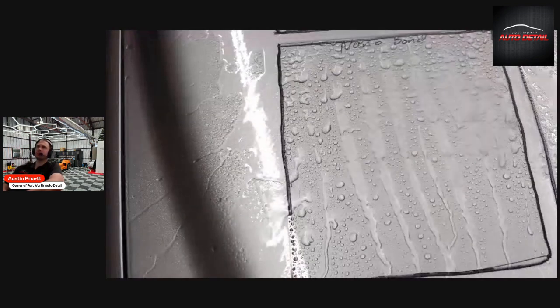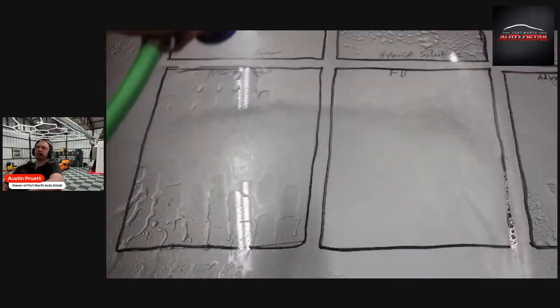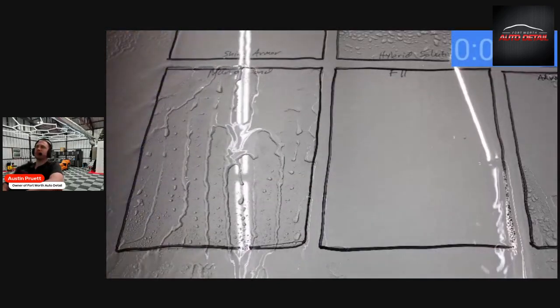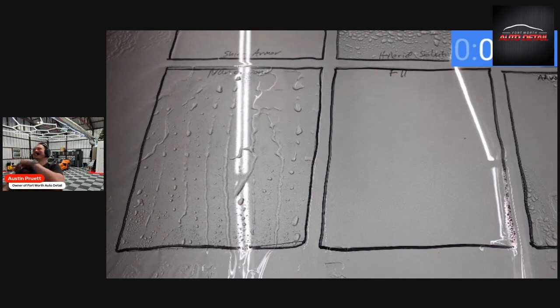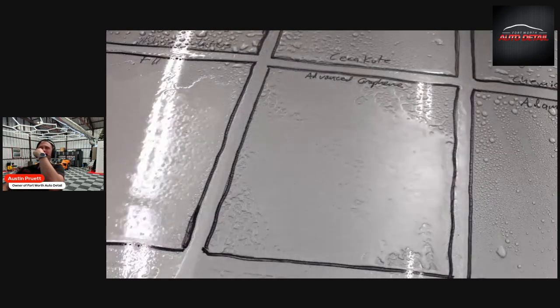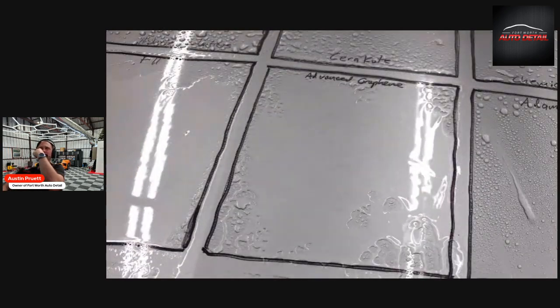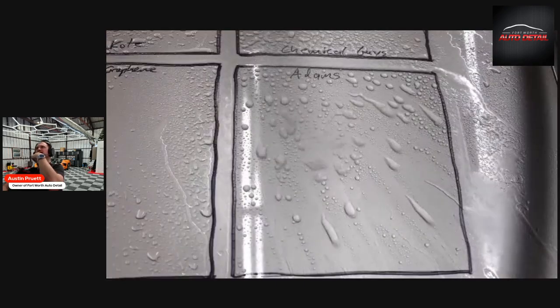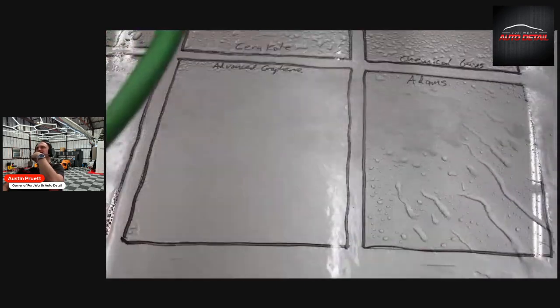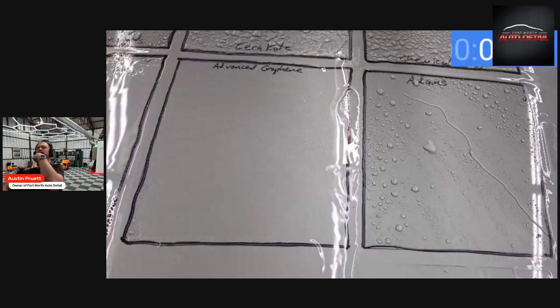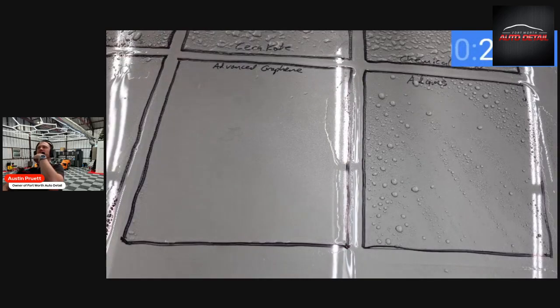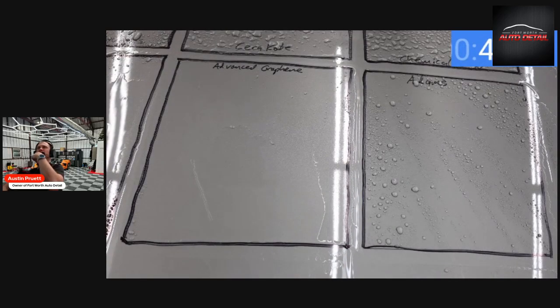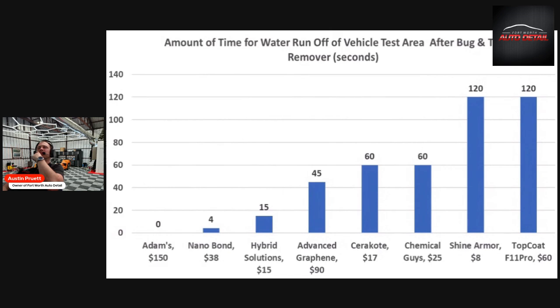And the Nanobond is performing even better than the hybrid solutions. And the F11 top coat appears to be completely used up, but the Nanobond is clearing up in only 4 seconds, the best yet. With a light water spray, water is quickly forming a sheet over top of the advanced graphene. And the Adam's still looks as good as new with only water beads. Even with the heavy water spray, water is still beading up on the Adam's. And it took close to 45 seconds for the water sheet to dissipate over the advanced graphene. So the Adam's remains on top without water forming a sheet over the Adam's, even with the heavy water spray. Nanobond finished in second place at 4 seconds, and Hybrid Solutions at 15 seconds.